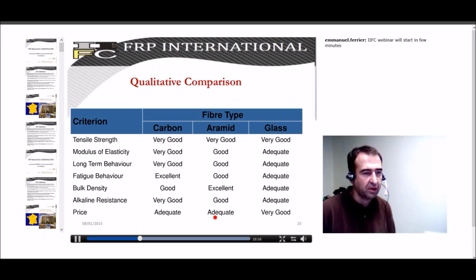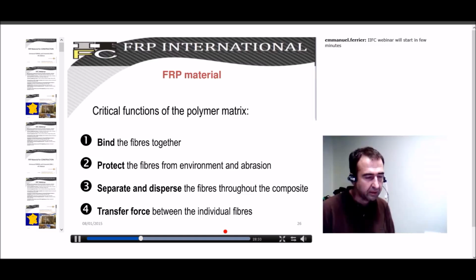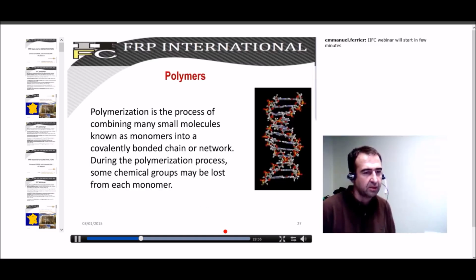If we look at these three kinds of fibers, there is carbon, aramid, and glass. Carbon has very good properties for all the mechanical and physical properties we may look at. Glass is also good, but the problem is the low Young modulus of this material and the long term creep sensitivity and also fatigue, which is less effective than carbon.